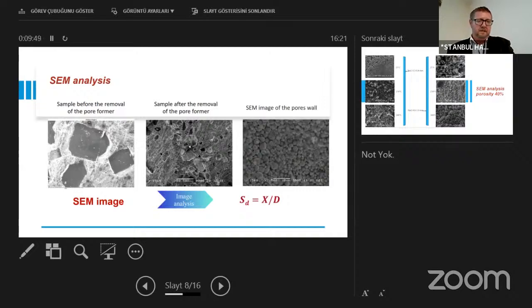Here I presented, on the left, a sample just after the cold sintering process. The rectangular shape is the salt, the others are the zinc particles—well, we cannot really see these particles. The middle one is after removal of the salt at a lower magnification, and the last one is an image presenting the pore walls.